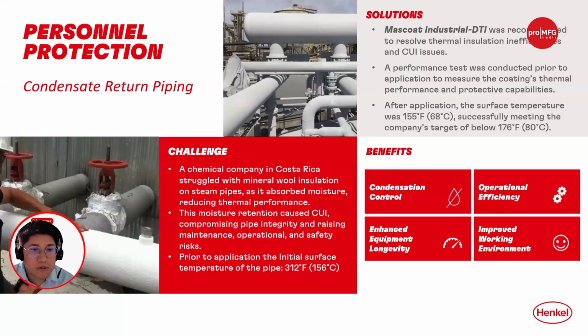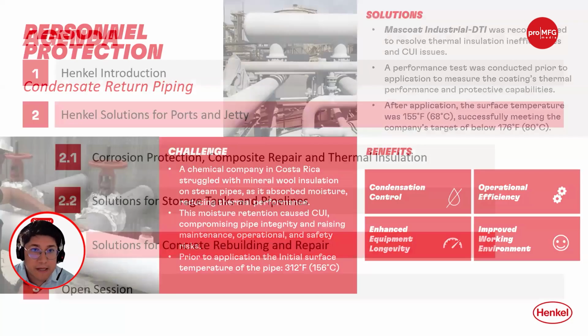So we proposed our Mascoat Industrial-DTI system that was sprayed and applied across the different pipes you can see, and not only pipes, but also heat exchangers and different types of equipment that were in this section. And we were able to reduce the temperature successfully from 156 degrees Celsius to 68 degrees, which was below the target of 80 that the customer originally had. Next, please.